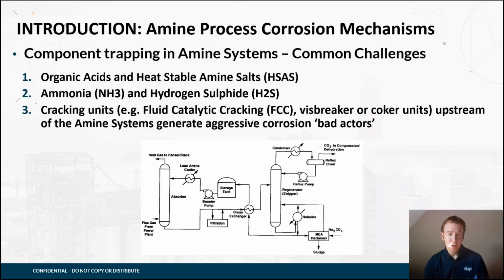We know they're there. We need to manage them by installing a barrier that is going to protect, not only in the high temperature regions, but also in regions where we have, for example, turbulence and velocities, where we can also see erosion-corrosion processes taking place and not just the pure corrosion. So the barrier system we employ needs to be suitable to operate in all these environments.